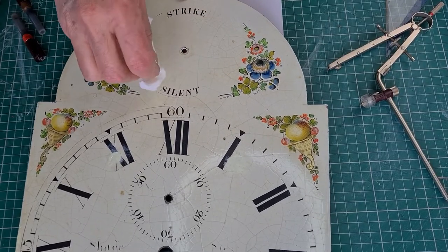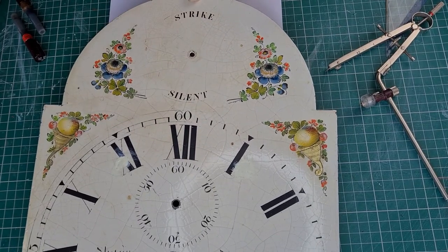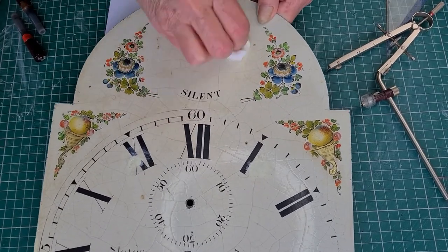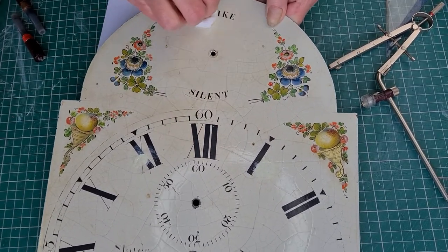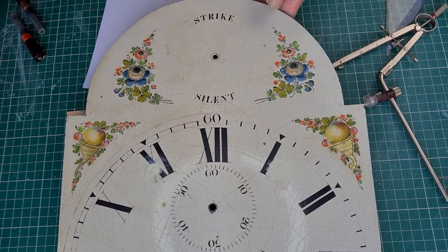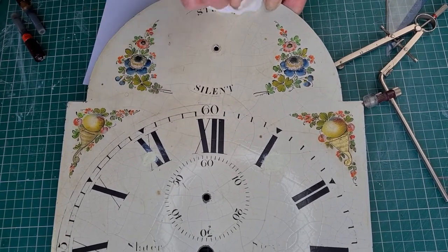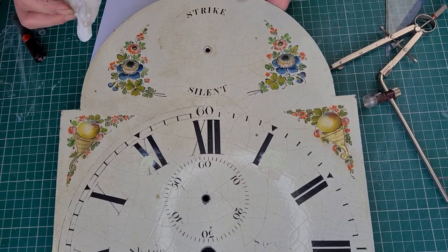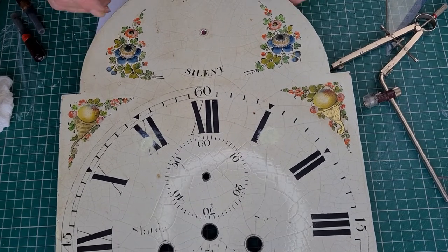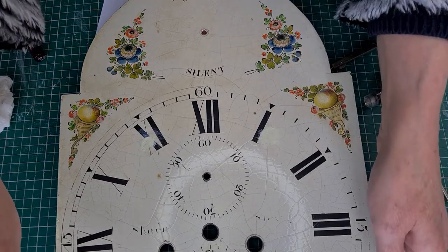quite hard actually, with distilled water, because I'm using shellac ink, Winsor & Newton's shellac ink. Don't use calligraphy ink, that's rubbish. You need the shellac, otherwise it doesn't dry waterproof. But unless this has absolutely got nothing on it, the ink won't stick. And also you need to use distilled or deionized water, because the ink will split with ordinary tap water. So I still need to prop the other end up a bit more. Just find something to prop.